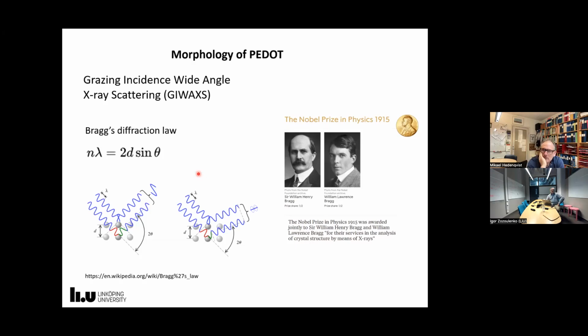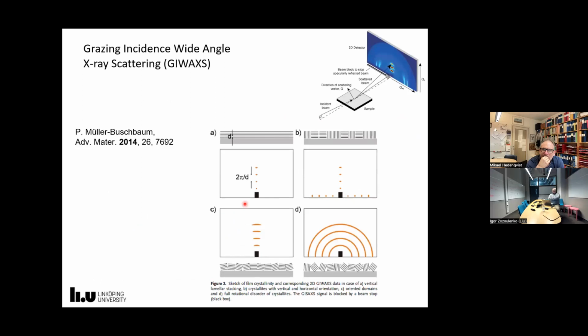morphology of the system? So here you use X-ray scattering and basically use interference phenomena. So depending on the wavelengths or the distance between crystallite planes, you can have constructive interference when 2 waves go into the same phase, and you can have destructive interference when waves go into opposite phases. Okay, and this is used in so-called grazing incidence wide-angle X-ray scattering. So typically, one places a conducting polymer or whatever material that one wants to investigate, and then one sees the following picture. And then, so how to interpret this picture?